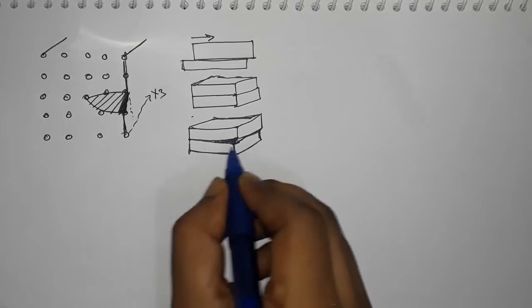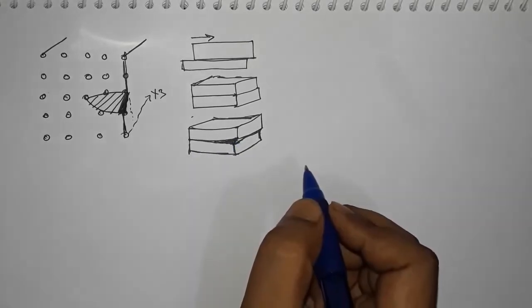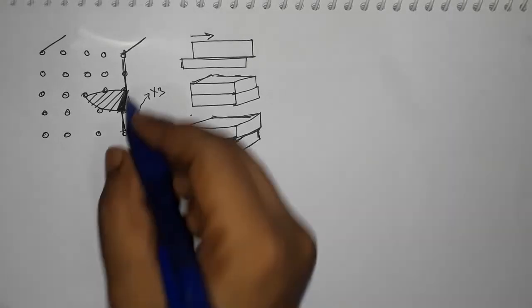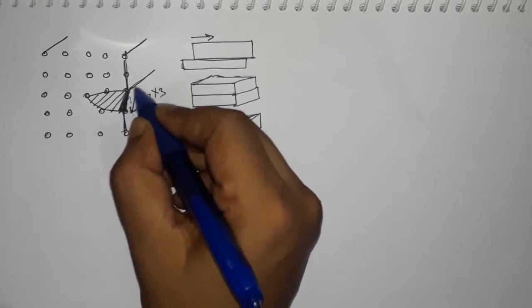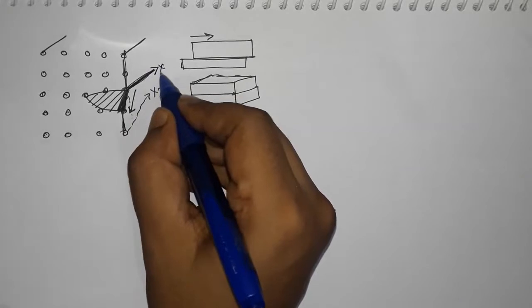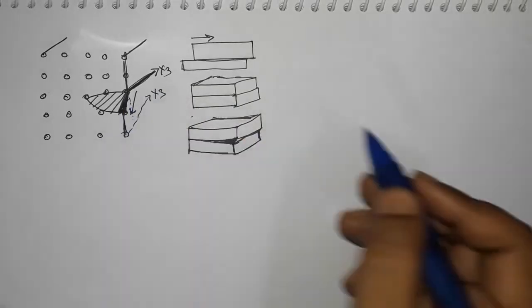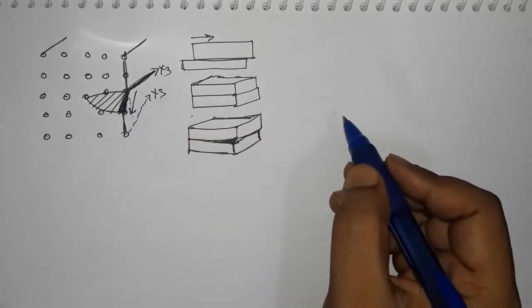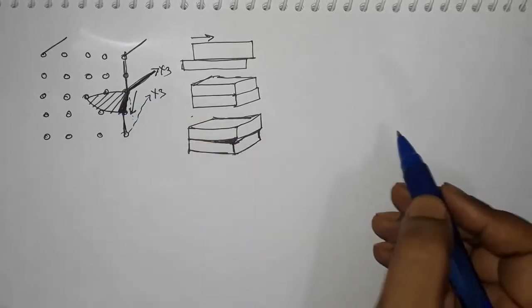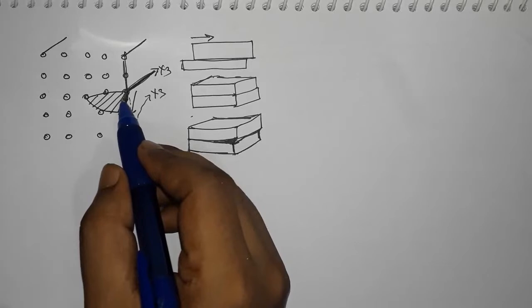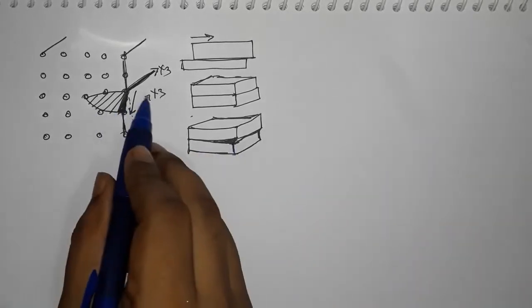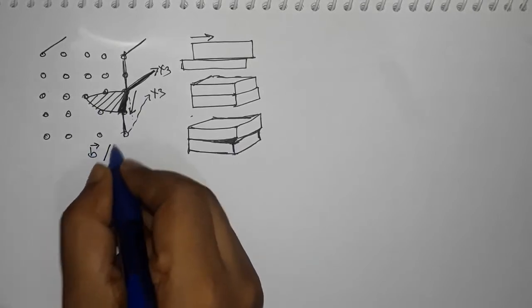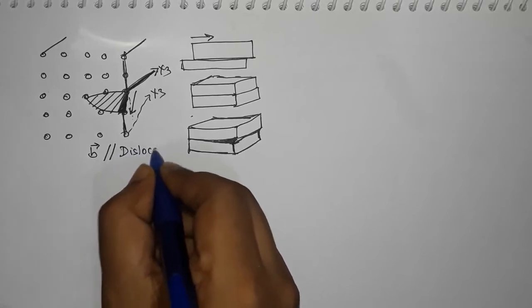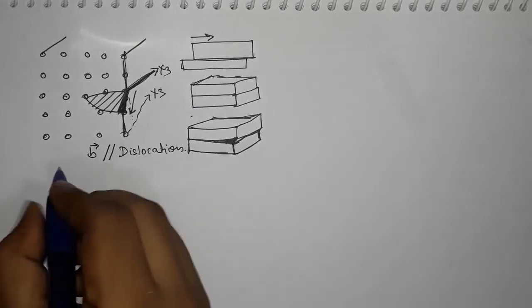Okay, so this is a different type of dislocation. In this case, the direction of the dislocation Burgers vector is in the x3 direction, and the line of dislocation is also in the x3 direction. It appears tilted here, but it is in the same direction. It's downward because I have a step there, but the dislocation line as well as the Burgers vector, along the direction where the atoms have displaced themselves, is in the same direction. So the Burgers vector is parallel to the dislocation line, and this type of dislocation is called screw dislocation.